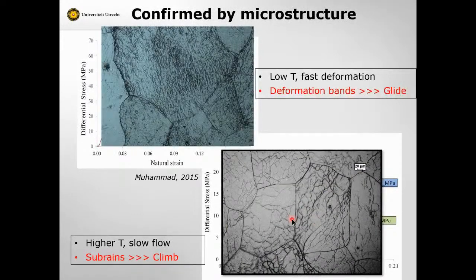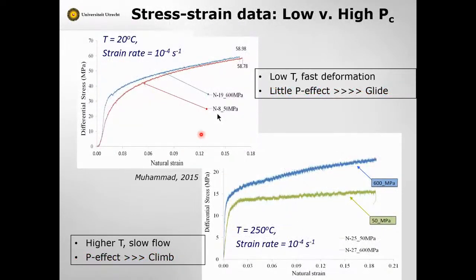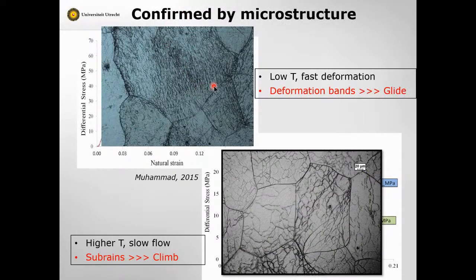You can see evidence of this. Here it is, look. So let's go back. This is low temperature fast, high temperature slow. And what you see in low temperature fast is these bands. To cut a long story short, these are bands where dislocations have moved through the crystal, consistent with the concept of glide controlled deformation. So low temperature deformation of salt, fast, involves an important component of glide.